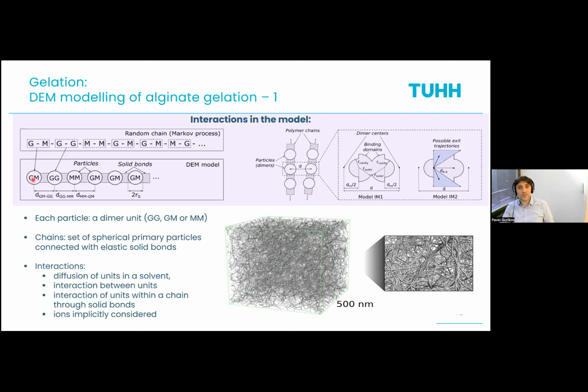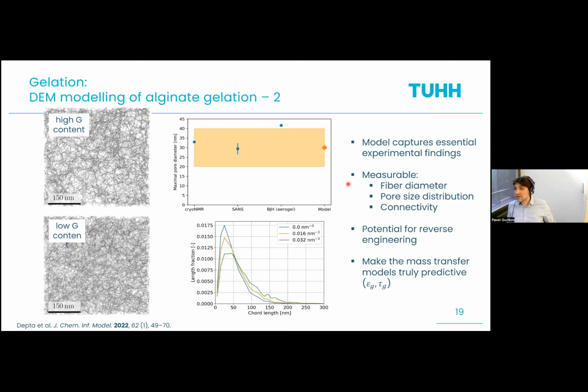And depending on the composition, which is here denoted G and M, it doesn't really matter what exactly it is. It's just two sugar residuals along the chain. You may ask yourself, what happens if I just substitute this G by M or this M by G? What happens if I change the chemical nature of the polymer I'm dealing with? And from the experimental results, you always know that when you have high G, then you have a more porous structure, and when you have low G, the mesh size is kind of smaller.